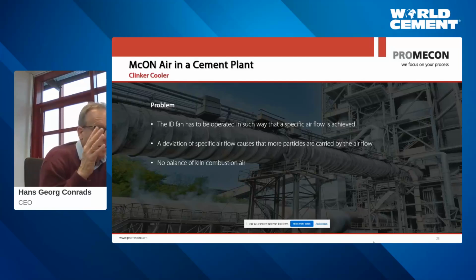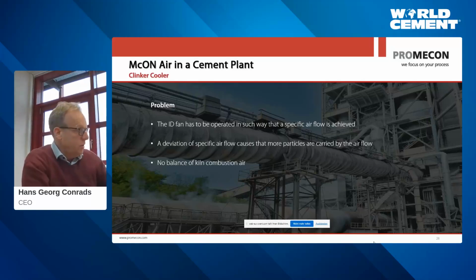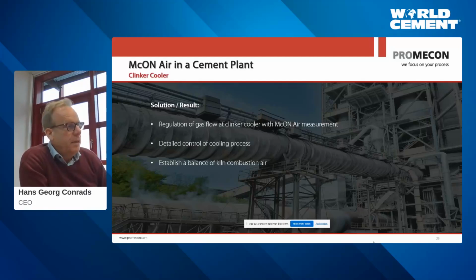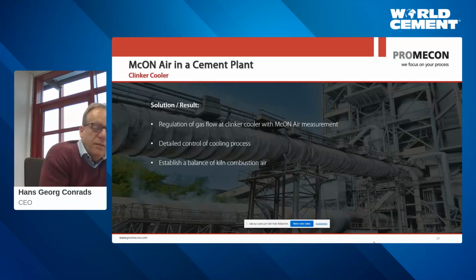Is all the air going to one side, or is the clinker cooler balanced and has the neutral zone in the middle? So all of this can be controlled far better by having a good mass energy balance over your clinker cooler. Remember, you have 2 ID fans, one at each side, one at the waste heat side and one at the downcomer side. And these ID fans need to be balanced, and a good gas flow balance in the clinker cooler is a big help for achieving this balance. And what's the benefit? The benefit, again, is a much better regulation. It is reduction of process noise. It is a lower energy consumption and a lower fuel consumption.